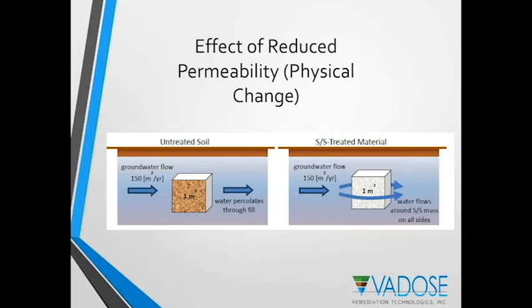Essentially, the purpose for changing the permeability or reducing the permeability is to reduce groundwater contact with that solidified mass. So as you can imagine, the illustration shows that as groundwater were to percolate through contaminated mass, you're going to be picking up contaminants as it flows through. And by reducing the permeability, you're able to redirect that flow around the solidified soil mass and reduce the mobility of those contaminants.